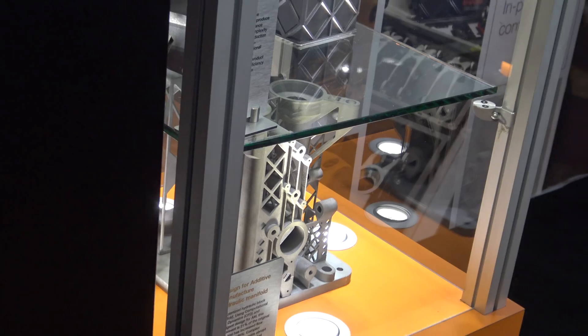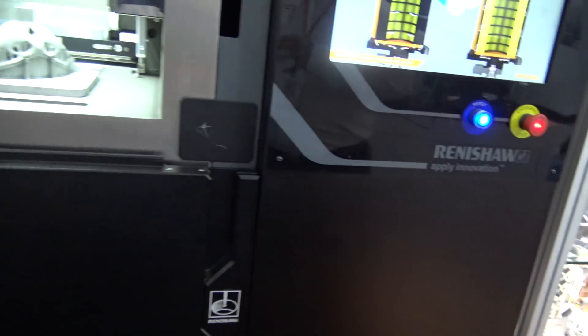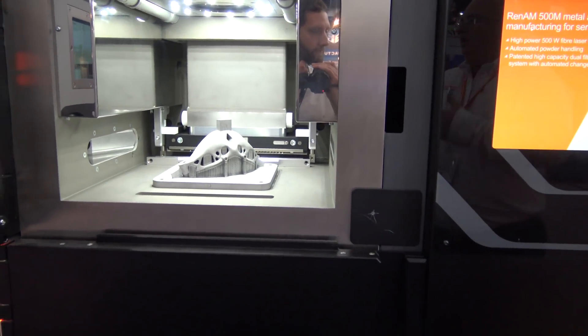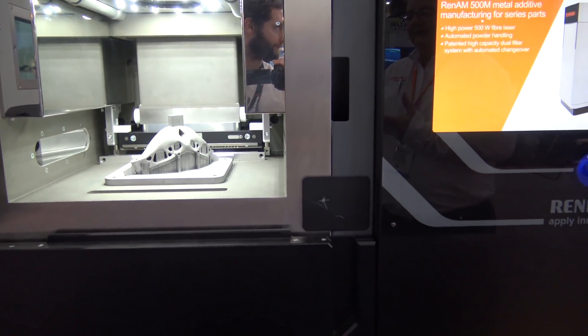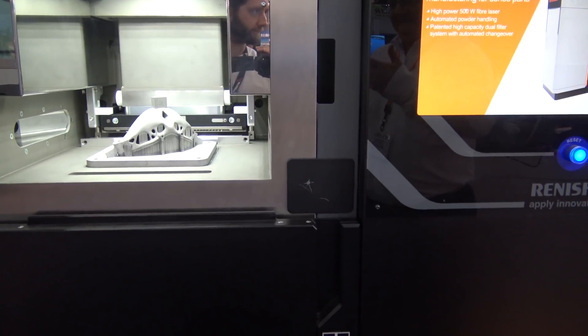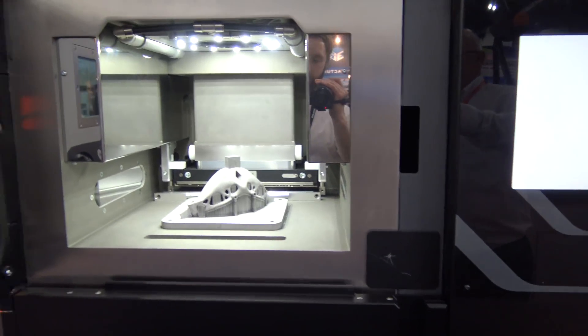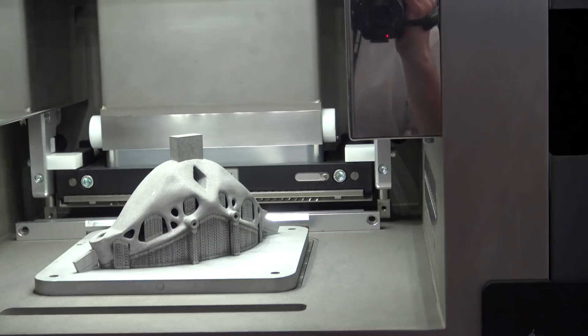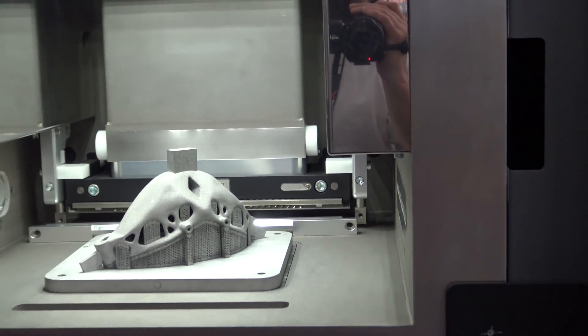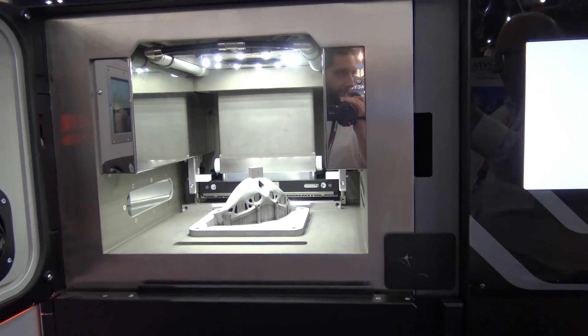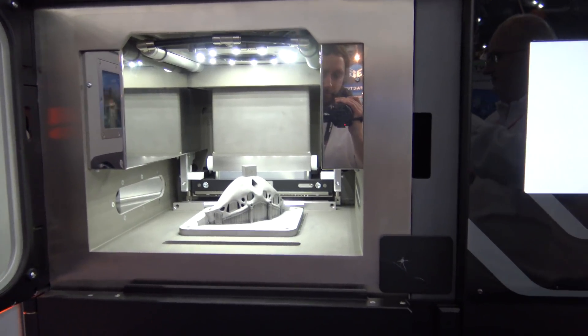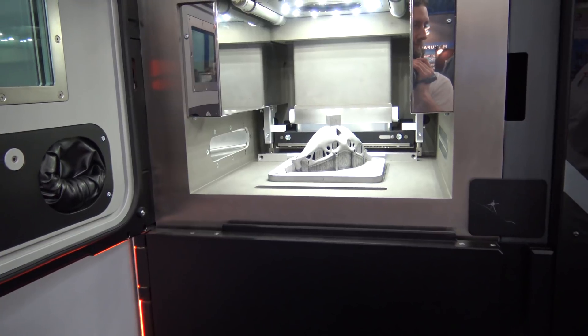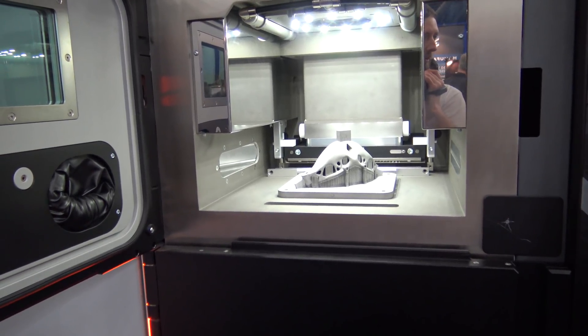What I'm referring to is if they're not a hollow structure but fairly solid. However, density, we don't like talking about density in terms of a print except for when we're talking about the density of the solid part of the material, because people say, well, how does this compare to a normal billet of that material? Actually, we've got it now with our own optics and fine tuning. We're within 0.1% of the same mechanical properties as a raw billet of that material, so we're very, very close.